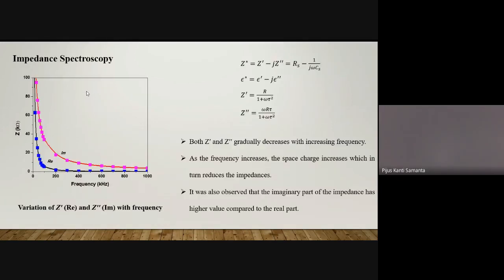We also studied the impedance spectroscopy to study the different contributions of grains, grain boundaries, and electrode-electrolyte interface effects on the impedance of the material. So this graph shows the frequency dependence of both the real and imaginary part of the impedance. And these formulas are well established, so I am not going into details. And this figure shows that both the real and imaginary impedance gradually decrease with increasing frequency. As we know, as we increase the frequency, obviously the space charge increases, which in turn reduces these impedances. It is also observed that the imaginary part of the impedance has a higher value compared to the real part.